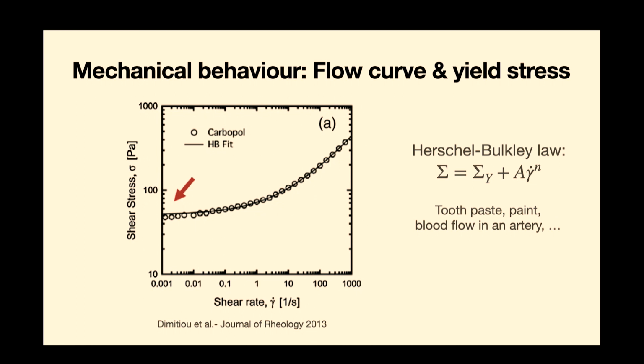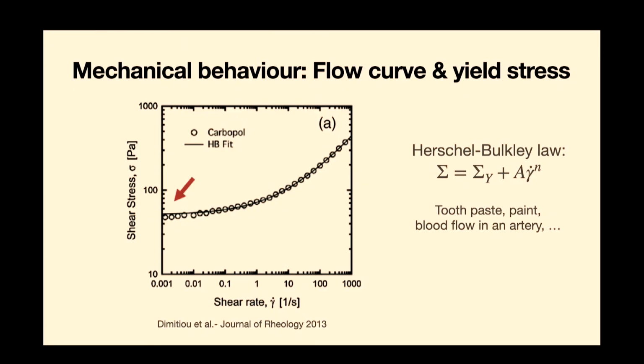We're going to look at a different protocol, which is oscillatory strain, which is a similar idea, but you do this with your plate. So you have a frequency and you have an amplitude that you can control. Okay? And what's interesting about that scenario compared to this one is that here all the states that I can explore that are steady states are the ones which are flowing. Okay? Whereas everything that's down here below the yield stress is never in a steady state. Right? Whereas with oscillatory strain, as we will see, there are steady states which are fluidized, so which are flowing, and there are steady states which are essentially elastic, right? So which have not yielded. Okay? And so that's one advantage of this oscillatory protocol.